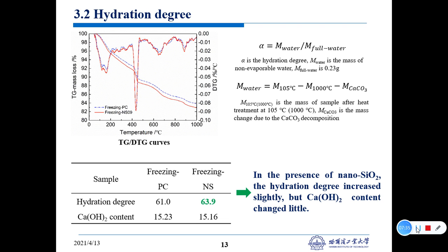This is the hydration degree. The TG and DTG curves are shown in this figure, and we use this formula to calculate the hydration degree. And we can see the hydration degree of the sample with nanosilica is slightly higher than the PC sample.